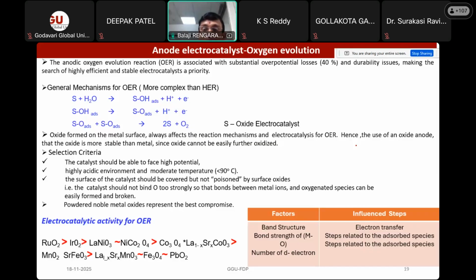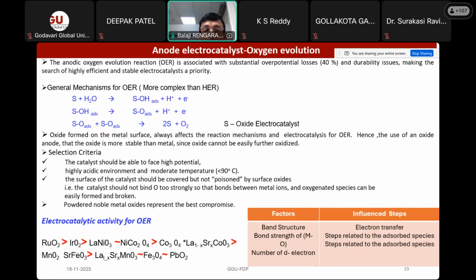So if you are able to develop a very good material which will reduce the resistance offered during the oxygen evolution, then you can considerably reduce the energy input for the hydrogen generation. So the anode electrocatalyst is also equally important. Depending upon the type of electrolyte, whether it is acidic or alkaline, you can choose the materials. And if you see the chart, ruthenium oxide and iridium oxide are the best electrocatalyst materials for the oxygen evolution when compared with the other electrocatalysts in this series.